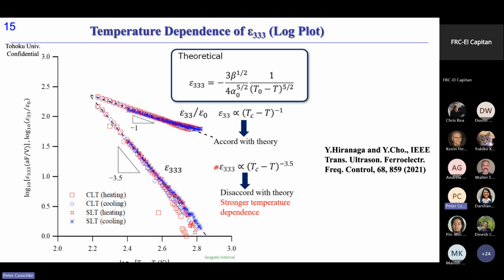But surprisingly, non-linear dielectric constant has a very strong temperature dependence. It is proportional to the minus 3.5 power of Tc minus T. So this means that if the temperature is approaching the Curie temperature, quite large non-linear dielectric constant can be expected. Of course, the reading speed of the SNDM method is proportional to the signal to noise ratio, and the signal is proportional to the magnitude of the nonlinear dielectric constant.